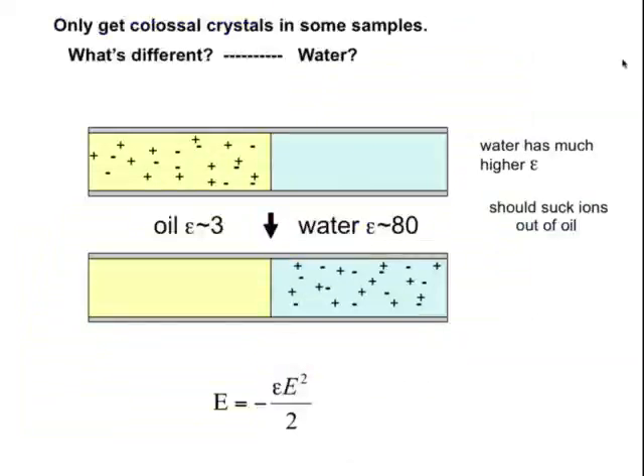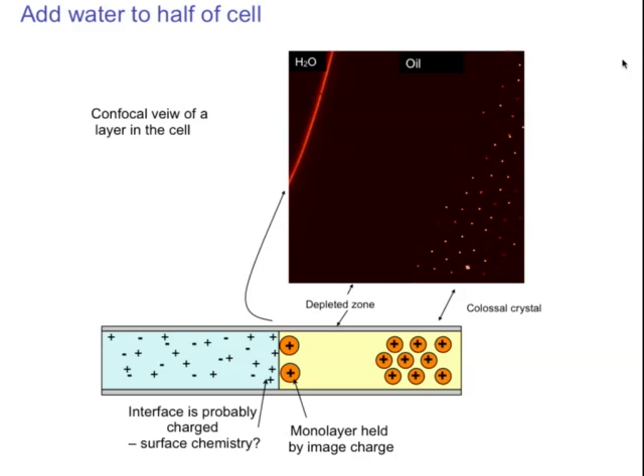So let me see. Here is what happens. You put the water in. Here's a drop of water in the system that I showed you before. When you put the drop of water in, you always get this colossal crystal over here with a very large screening length, with a large screened Coulomb interaction, almost unscreened between the ions. But you get something else as well. First, here's the water droplet. You have a depleted zone over here where there are none of these colloids, and right next to the water you have a monolayer of the colloids, right?